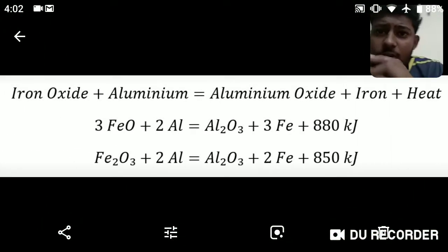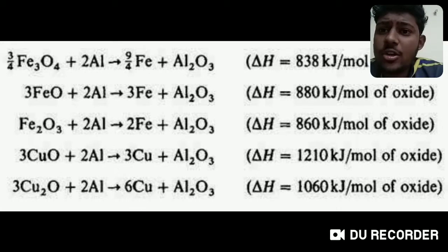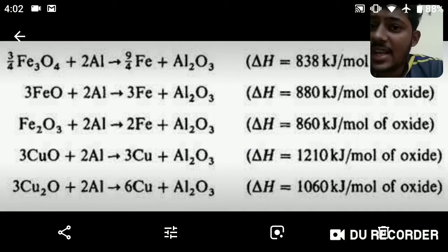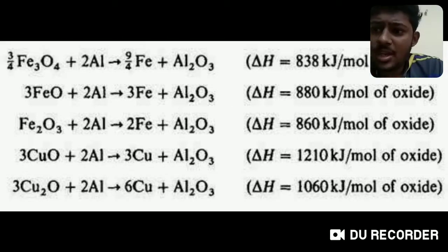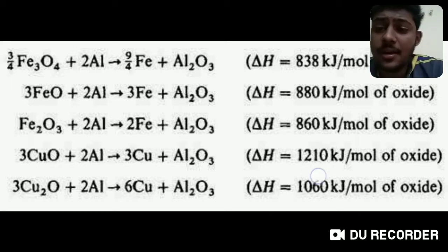This is not only limited to railway tracks. In the case of railway tracks, we generally use an iron oxide and aluminum mixture. In order to weld high tension copper wires or very thick copper cables, a thermit mixture is also used, but the mixture used is copper oxide and aluminum. The process is simple. The aluminum replaces the oxygen, and the pure copper settles below, while the aluminum floats above and gets separated as slag. This way thermit mixture welding is done.